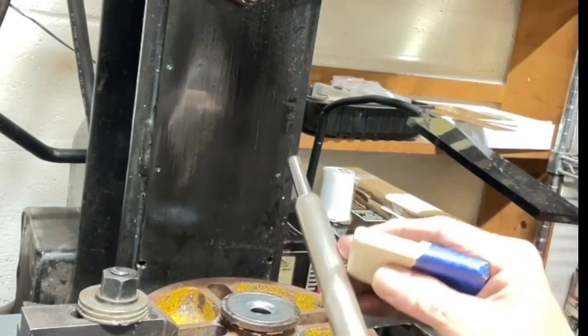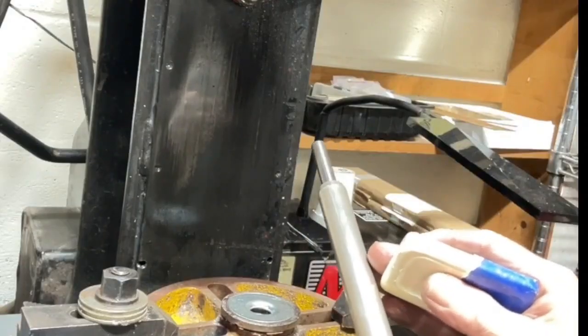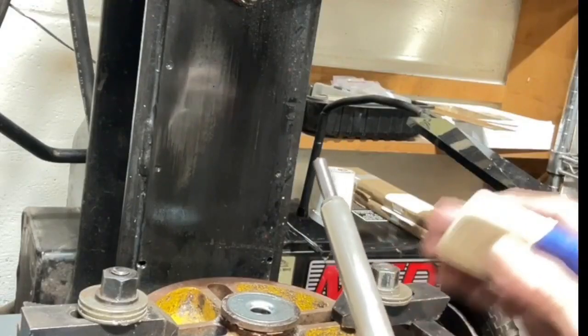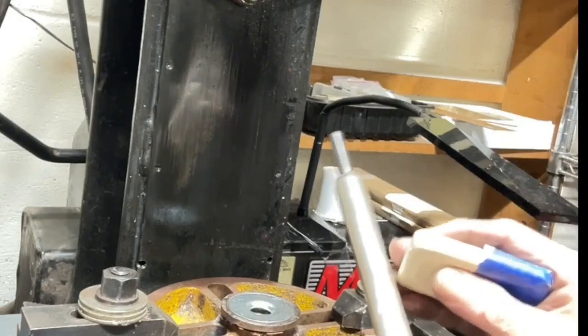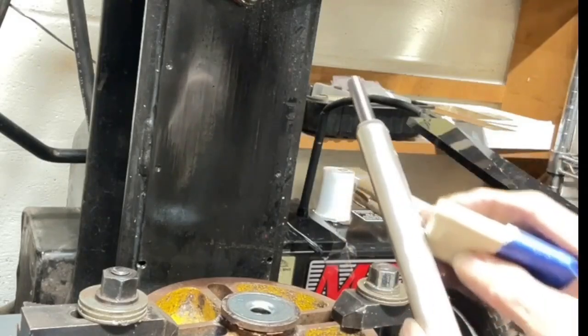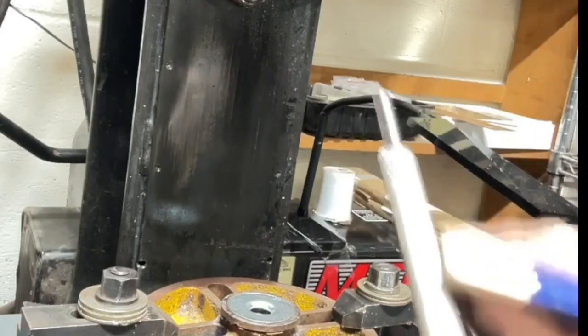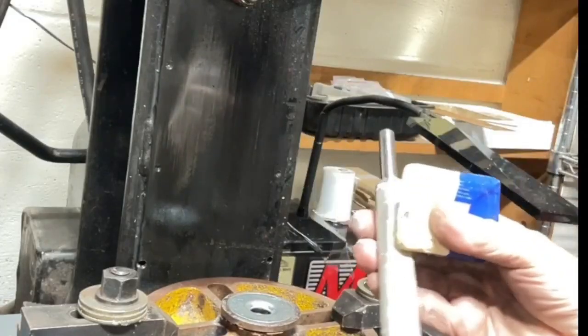I've tried every kind of lubricant over the years, and with the exception of platinum tubes, which do require a special lubricant both inside and out because it's very prone to galling, the best lubricant that I've found is soap. I prefer Ivory soap, something that has a decent fat content in it, and I will coat the entire tube with that.